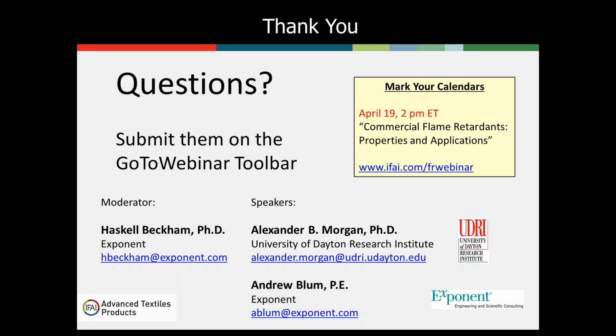Okay, so let me answer the first question. I think that really depends upon the chemical flame retardant you're going to use. There are some chemicals out there that may require surface preparation of the fabric so that they adhere better to the polyester, so that it becomes launder durable. And it's like any coating applied to something else. If the surface chemistry isn't right, it's like when you paint your walls. If you don't prime it properly or wash it properly, the paint doesn't stick properly. So the same thing would be true for certain flame retardant chemicals. If you don't treat the surface of the fabric correctly, the chemical won't adhere, and then it will come back off again, and you lose some of the durability.